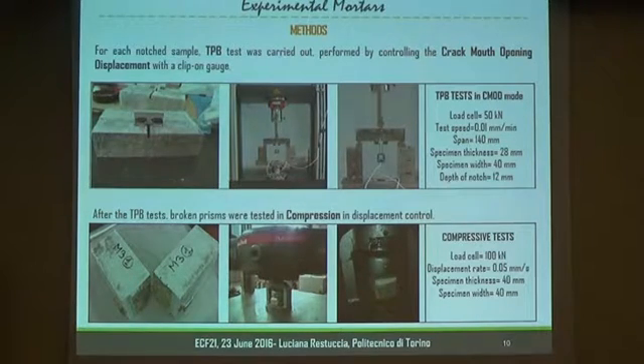Every specimen was notched, and for each notched sample, the three-point bending test was carried out, performed by controlling the crack mouth opening displacement with a clip-on gauge. After the TPB test, broken prisms were tested in compression in displacement control.